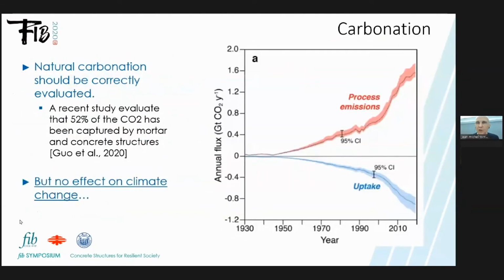Carbonation is the last part I want to discuss. Of course, we know that concrete carbonates, and we need to have a correct evaluation of natural carbonation. There was recently a publication by Guo showing that around 50% of the CO2 emitted has been captured by mortar and concrete structures. Here you have the emission, and here you have the uptake, and you see that we are around